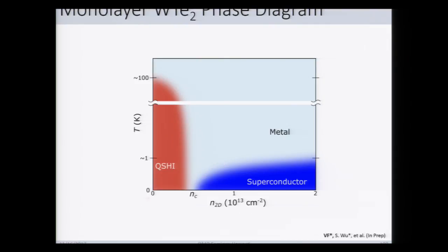And this allows us to draw an initial preliminary schematic phase diagram with temperature and density here. We know about the quantum spin Hall phase that can dominate the transport of the system up to 100 Kelvin, and the superconducting state that exists up to about 1 Kelvin for all high densities, and this metallic phase in between.